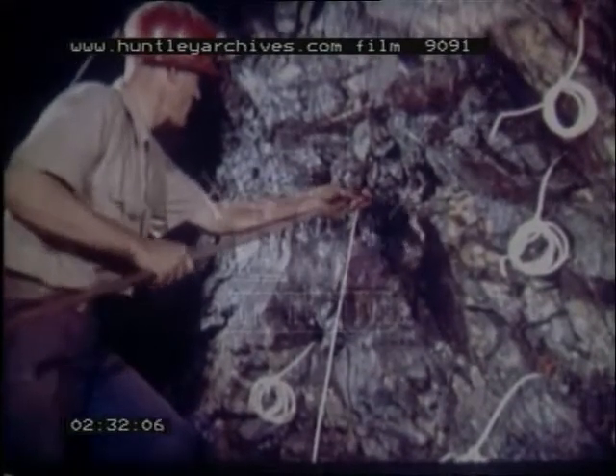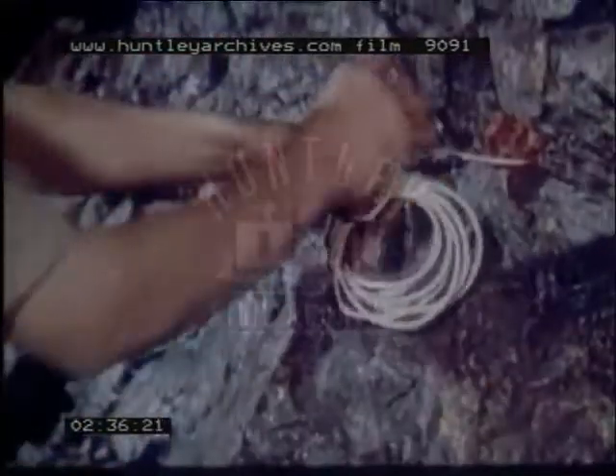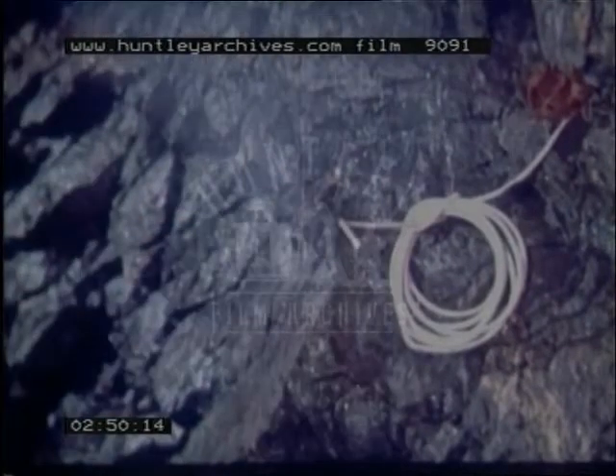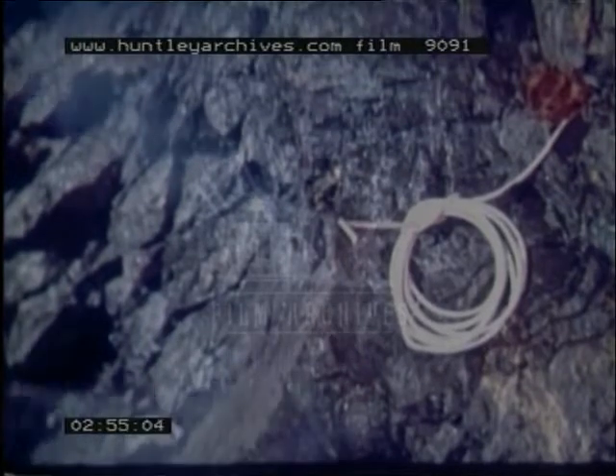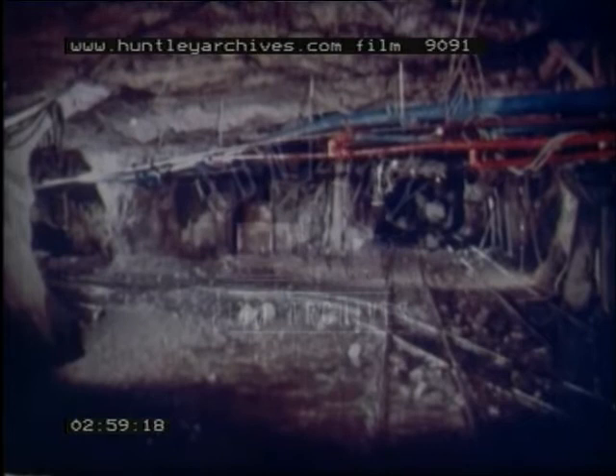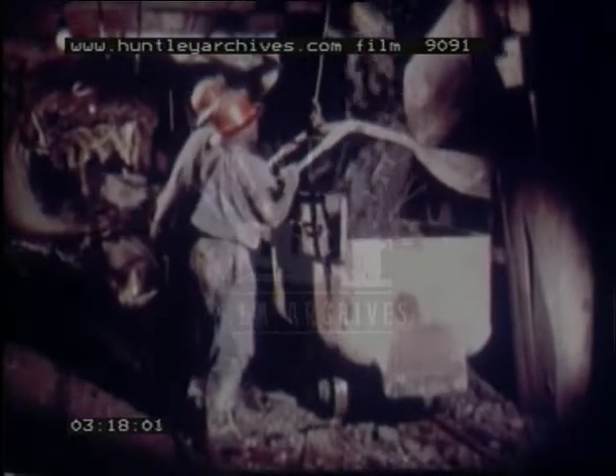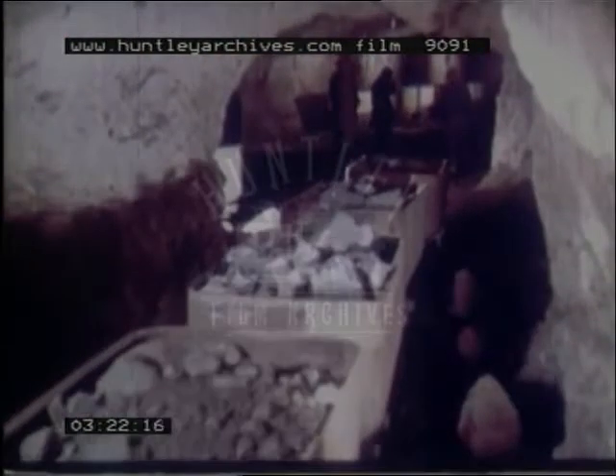The shot firer puts the charge in the blast hole, connects the fuse, and rolls it to ensure sufficient burning time. As soon as the fuse is lit, the occupants immediately leave the area. The contents of the trucks are tipped into a skip, which hoists 5 tons at a time to the surface.